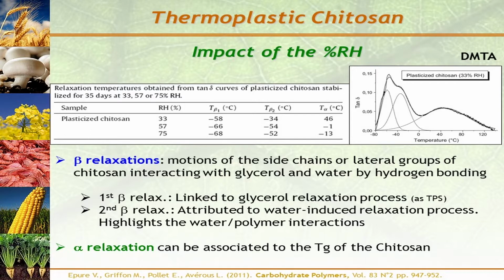Here is an example on the transition temperature determined by DMTA, depending on the relative humidity of the storage of your material. And you see that, I will not go into detail of all the relaxation temperatures, but this one is more due to glycerol, and this one to chitosan. And you see that it varies a lot depending on the humidity of the storage of the processing aging. And the highest humidity giving the highest water content of the material, leading to a lower Tg of your material.